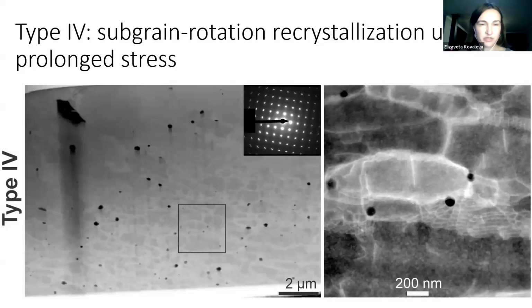This is the same grain, but in a different imaging mode. The bright lines represent subgrain boundaries. And the diffraction image shows that it is a single crystal, which was subjected to prolonged stress. And you need some kind of high differential stress to achieve this. And it's not usually looking like this under normal tectonic conditions.